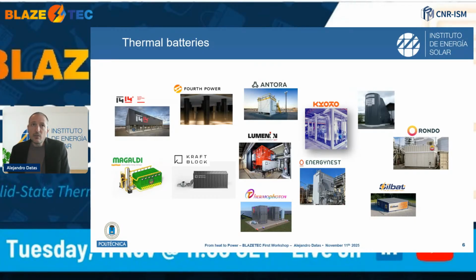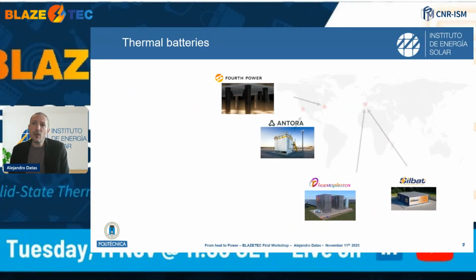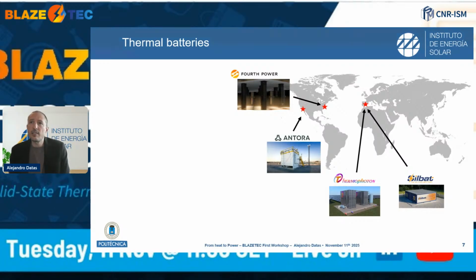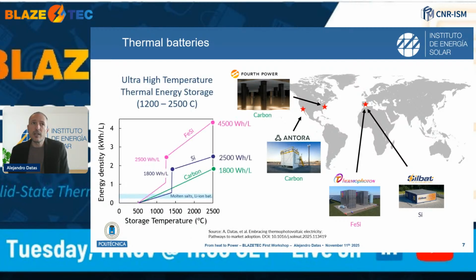But in this talk, I wanted to focus on a specific kind or subsector of these companies. Let me talk about these four. These are two based in the US and two based in Spain. The first common characteristic of these four companies is that they use ultra high temperature storage materials. So they store energy at extremely high temperatures. And in this case, you can see that the energy density can be very, very high depending on the temperature you reach, and the delivered temperature. You can reach even 4500 watt hours per liter, which is orders of magnitude greater than, for instance, molten salts or lithium-ion batteries. Just as an example.